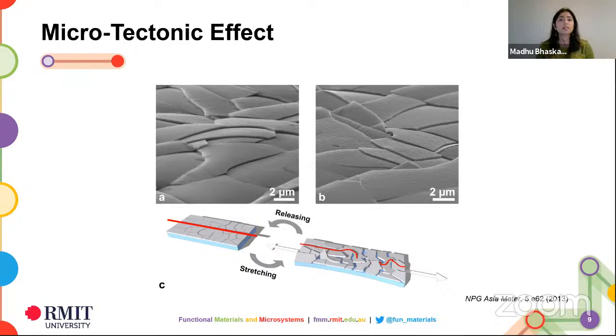Now, the beauty behind this was the fact that we put this in a scanning electron microscope, and we found that the oxide layer is no longer a continuous thin film. What you see over there is kind of an overlapping plate structure. So it's no longer a thin film, it's not cracked, but instead what you have is an overlapping plate structure. Now that's really, really unique, because what that allows it to do is, when you stretch it, the plates slide on top of each other. And as long as the strain value is still allowing electrical connectivity between the plates, it is still behaving normally.